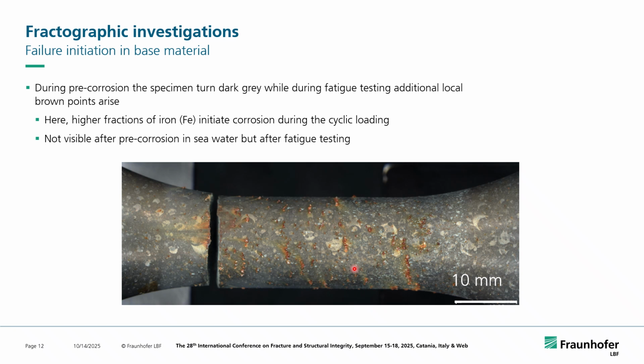a change, a little bit, in the microstructure and the corrosion signs that we see on the surface when we have really small quantities more of iron in the alloy, which are subjected to regular imbalances in the manufacturing process, but are still within the specification. And we kept this range really short.